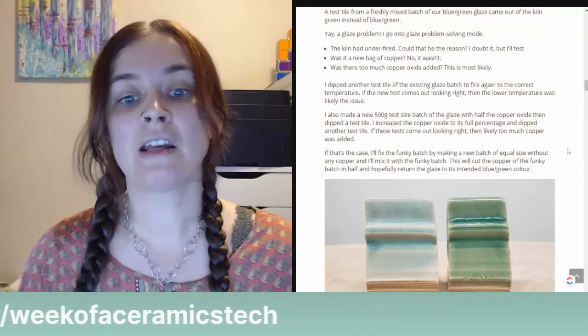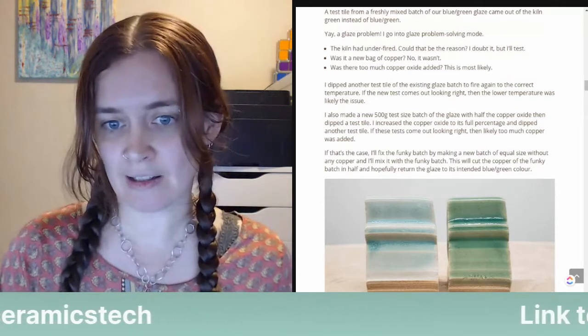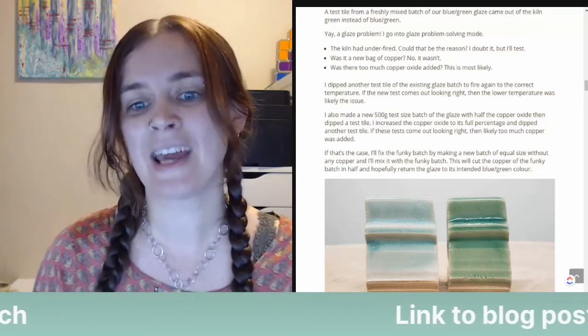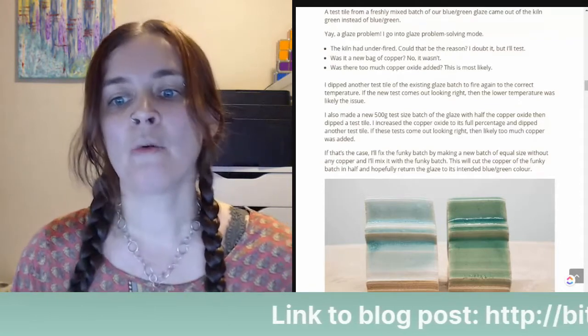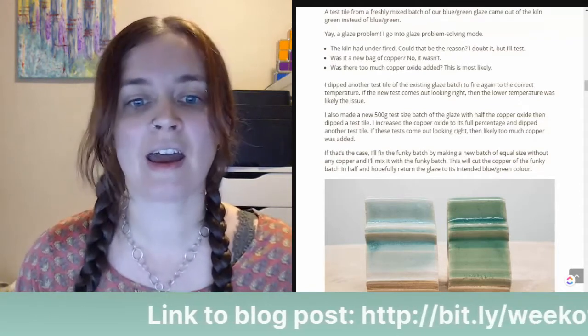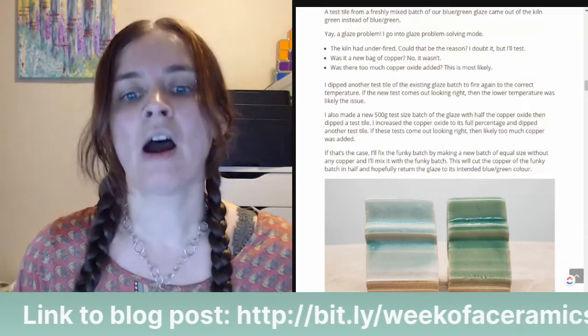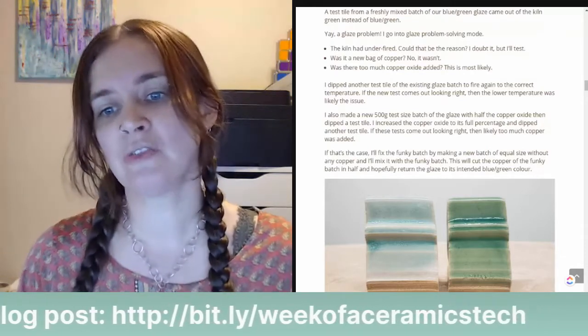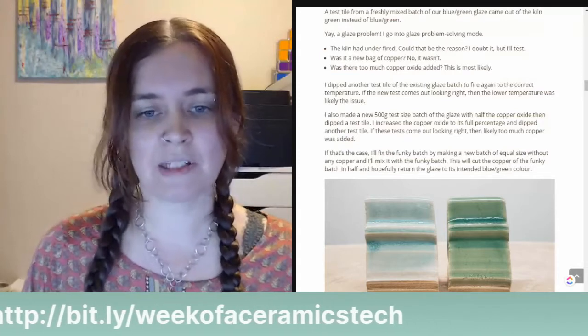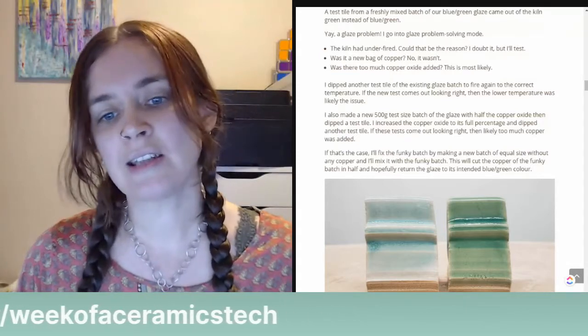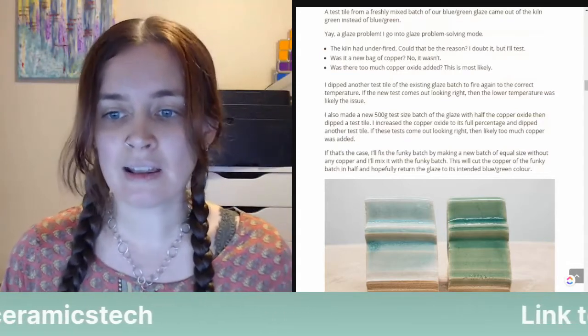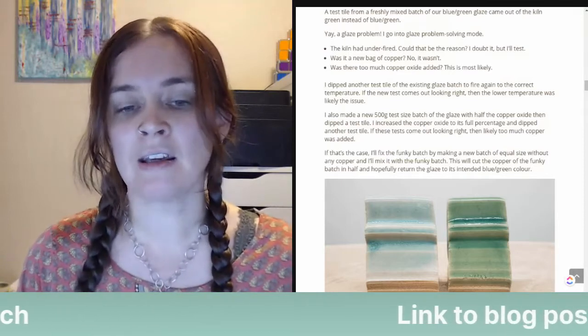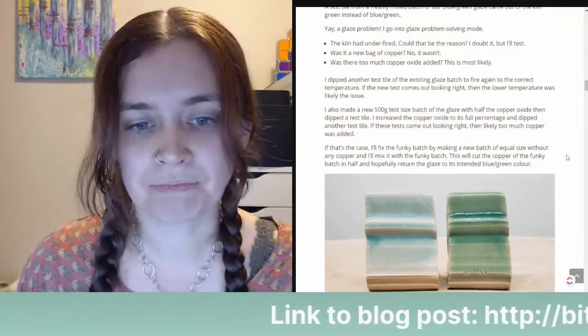I also made a new 500-gram test size batch of the glaze with half the copper oxide, and then I dipped a test tile. I increased the copper oxide to its full percentage, and then I dipped another test tile. If these tests come out looking right, then likely too much copper was added to that larger batch.